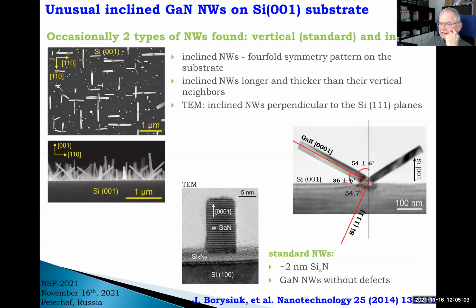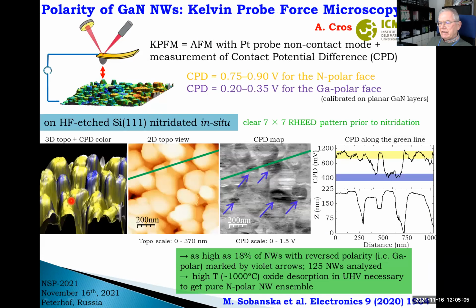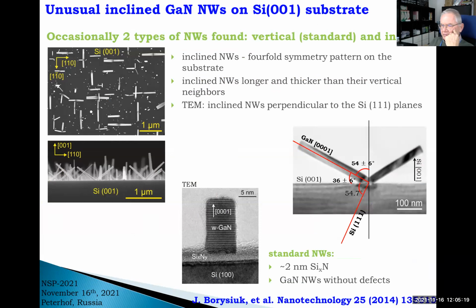Okay, now the question is how we explain this. There must be some oxide left on the surface, and how it causes reverse polarity. And for this we will refer to our previous paper, in which we also used HF treated substrates. This was silicon 001 in this particular case. And we observed that quite often we have in such a substrate two systems of nanowires.